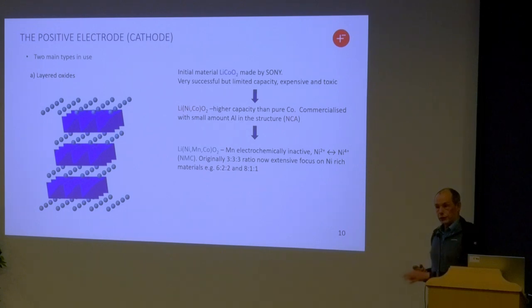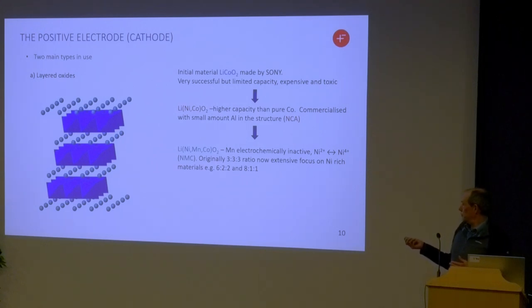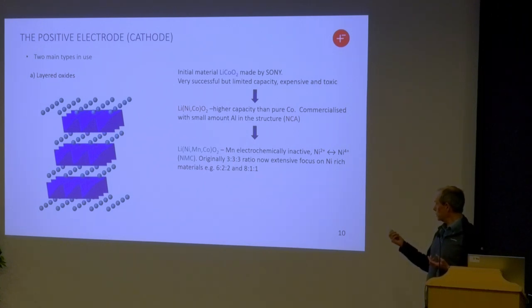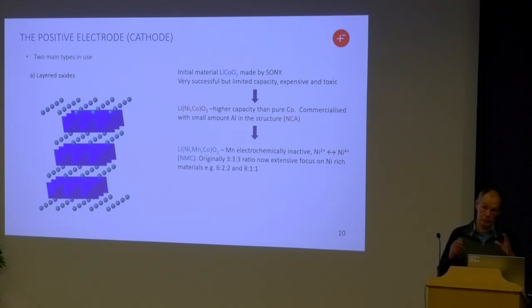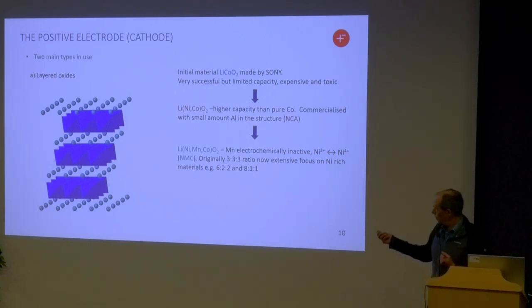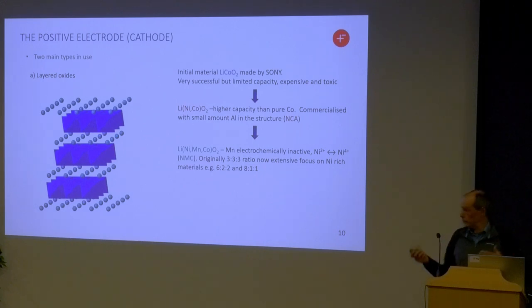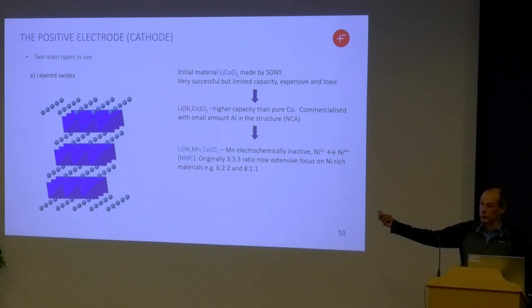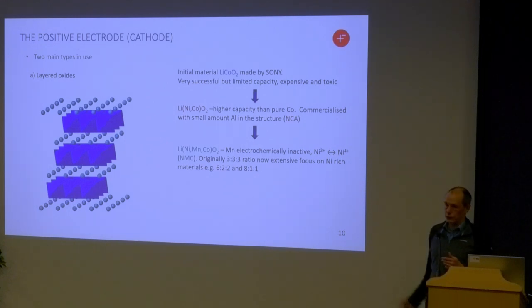As people want to reduce the amount of cobalt in the battery, people have been trying to change the composition, moving to what are called nickel-rich materials. So nickel to manganese to cobalt ratio is 6:2:2, and now they're really pushing to go to 8:1:1. So almost all nickel. In that case, you're using more nickel 3 plus to nickel 4 plus. But it comes with problems. If it worked as well as lithium cobalt oxide, people would have done it some time ago. So people are working very hard at particularly looking at trying to reduce the reactions of this with the electrolyte to ensure that it gives you the cycle life that's comparable to lithium cobalt oxide.